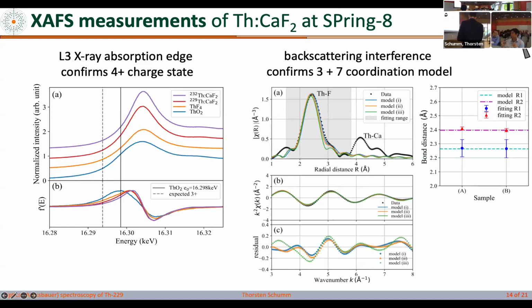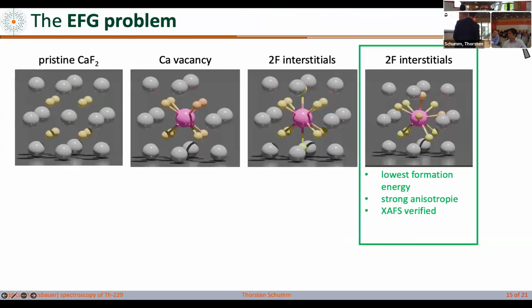Okay, and by looking at this, and I won't bother you with the details, it's a very advanced, very sophisticated method. People have been doing this for many, many decades. We can actually indeed confirm, yes, we find exactly this configuration. Here, there's 3 fluorides which are a little bit closer, and then there are 7 which are a little bit further out. And that gives us great confidence that, oh yes, we believe that if I were able to zoom into this material, I would find this to be the dominating environment. And you remember we have these 4 lines. These 4 lines correspond to one type of defect. There were two weak lines that we didn't investigate yet, but maybe these are other types of defects.